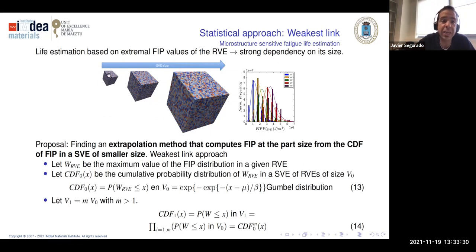You can see here, this is the probability of the fatigue indicator parameter to occur. The same simulation, just changing the RVE size, the probability moves to the right. So it means that the life prediction of this small or this big RVE will change. So what we want to do is get rid of the RVE effect using some extrapolation methods. The key is, instead of having a single RVE, we're going to use 100 of them, what we call a statistical volume element.